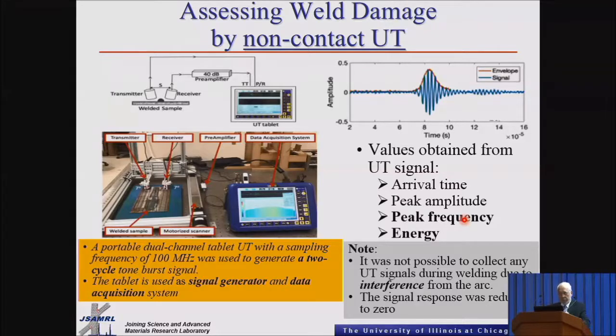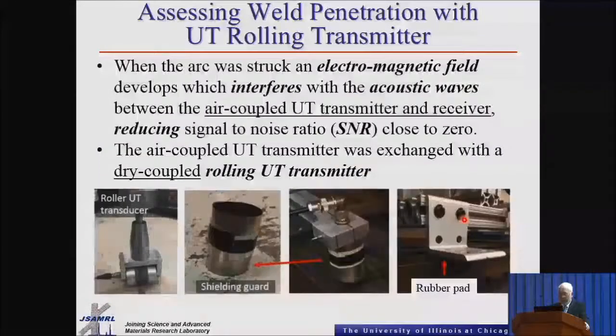What happens is when we start the arc, the signal all of a sudden was interfered with, so the signal disappeared and went to zero. We tried several times and tried to do some isolation of the sensors, and still no luck. So we decided to make some changes. Instead of using the non-contact, we used some type of rolling transmitter, as you can see right in here. It was the rolling transmitter that we adapted, coming after the weld.